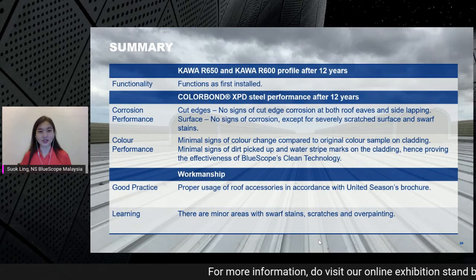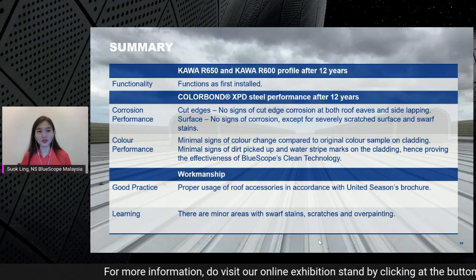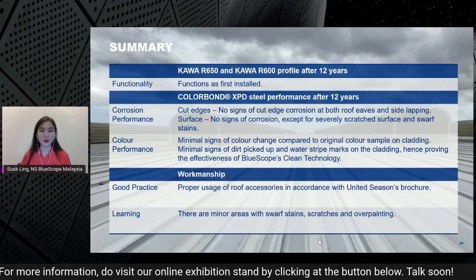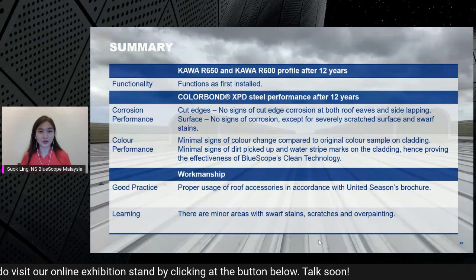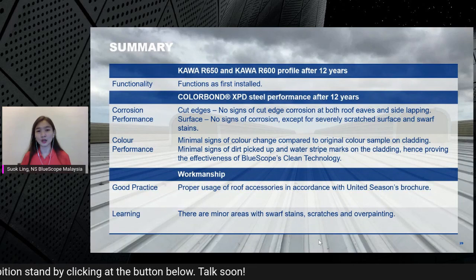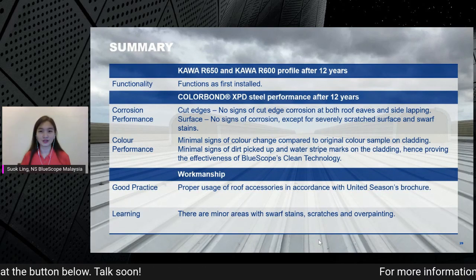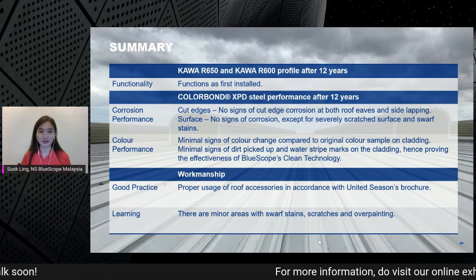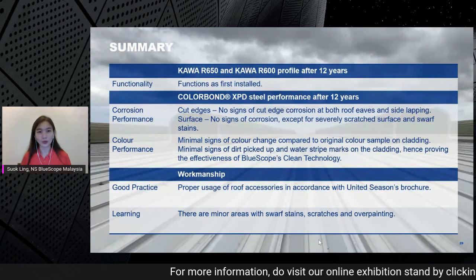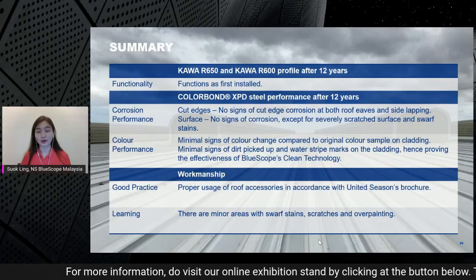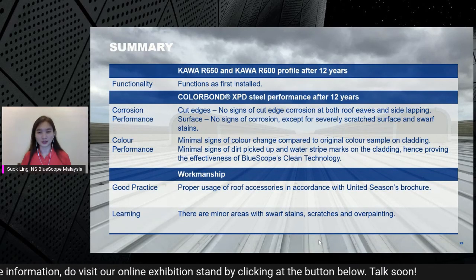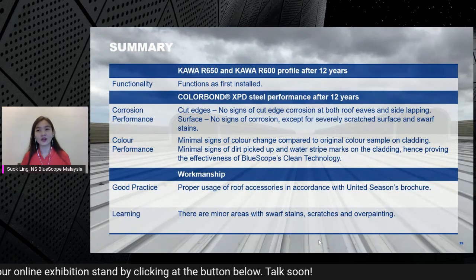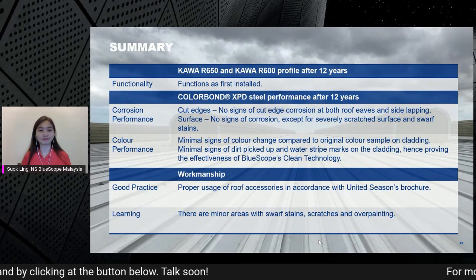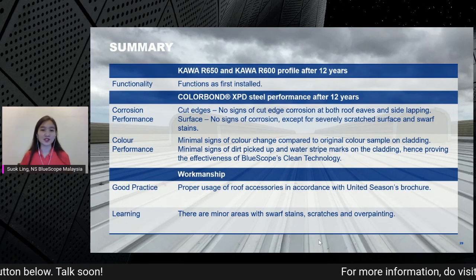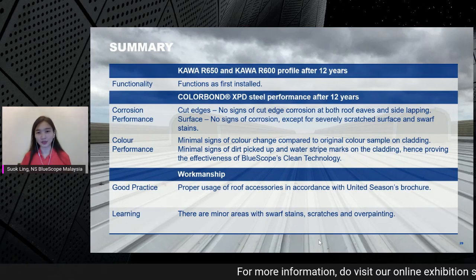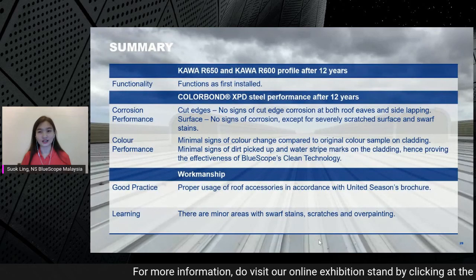So in terms of the summary of the materials performance, by looking at the corrosion performance, there is no sign of red rusting corrosion noticed over the cut edges for both the roof eave and also the side lapping. And on the surface, we also didn't notice any sign of red rusting corrosion, except for those certain areas with severe scratches and some swarf stains. And in terms of color performance, I would say a minimal color change has been noticed compared to the original color sample panel.